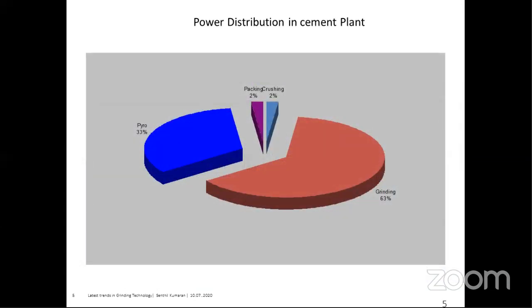When we see the power split in the cement plant, only 33% of the power is spent in the pyro operation, 2% in the packing plant, and 2% for the crushing. A major 63% is due to the grinding. So that's why the grinding operation is so important, that we have to optimize it and choose a proper solution for the grinding.